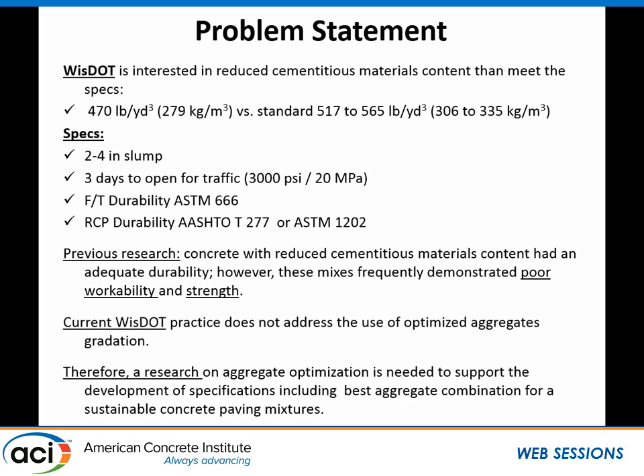So the problem is, Wisconsin DOT is interested in reducing cement content by 10%. Currently, they're using about 520 to 565 pounds per cubic yard. That's what the spec is talking about. They also would like to meet the requirements for workability, for opening to traffic in a short time, and then durability. The reason we're concentrating on aggregate packing is that the previous research they accomplished showed the mixtures developed did show poor workability, and there was no attention to optimizing the aggregate blend, and many of the mixtures using supplementary cementitious material had low strength.